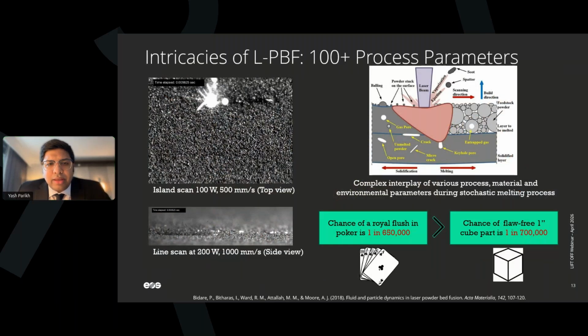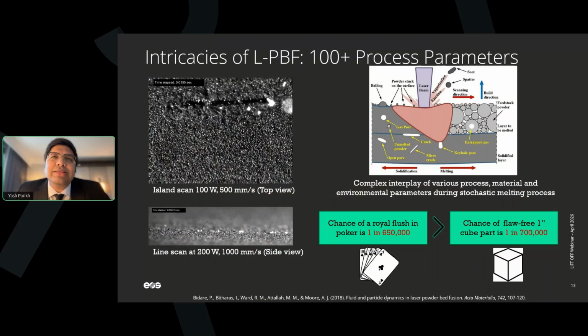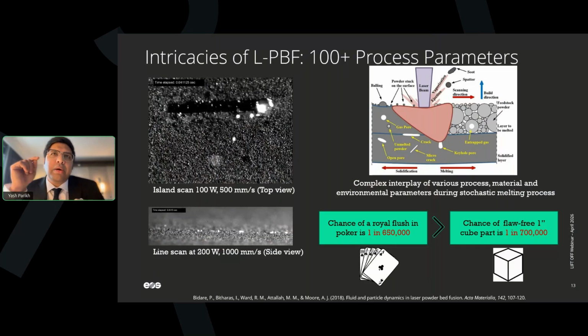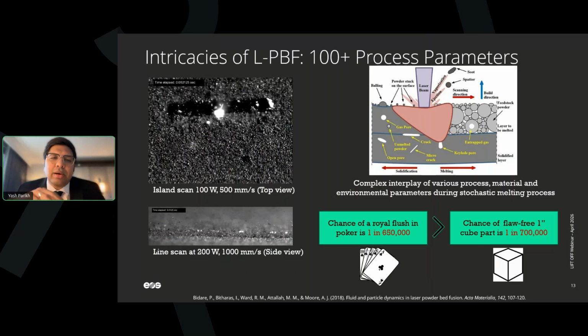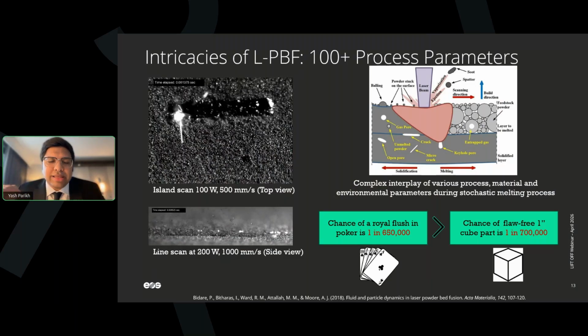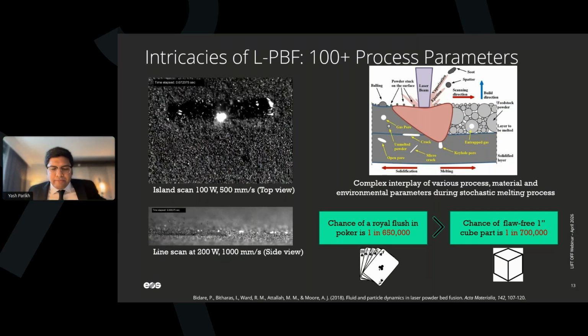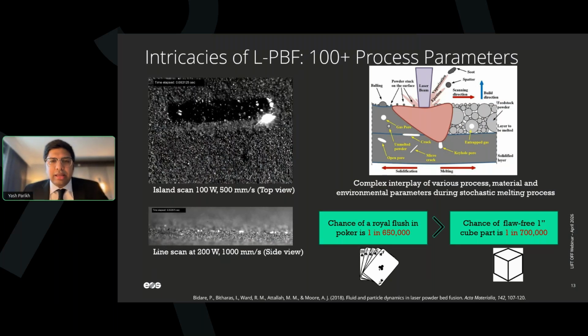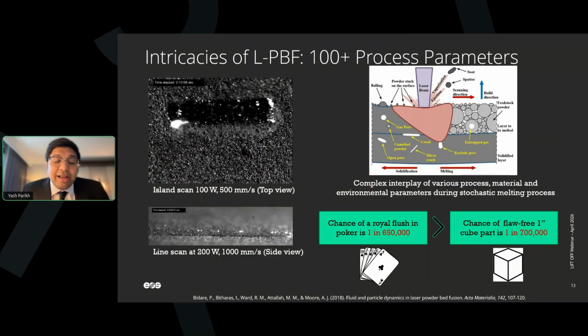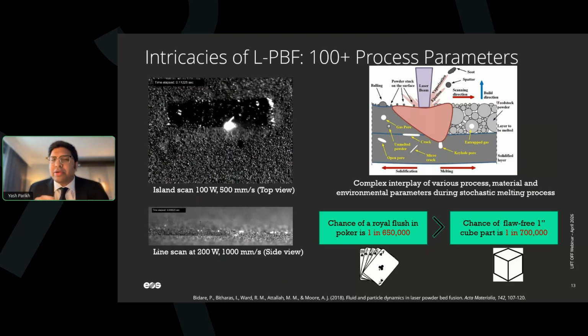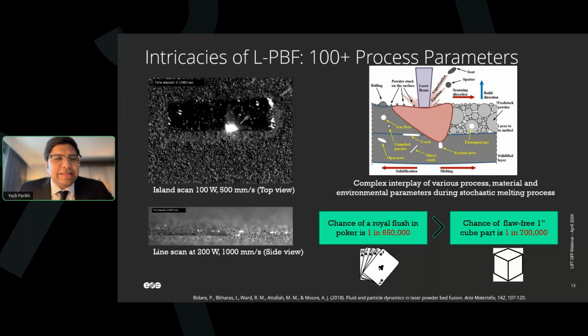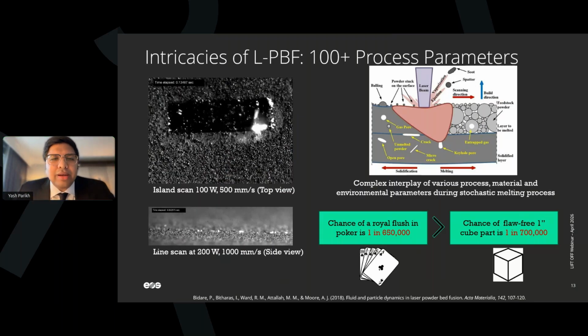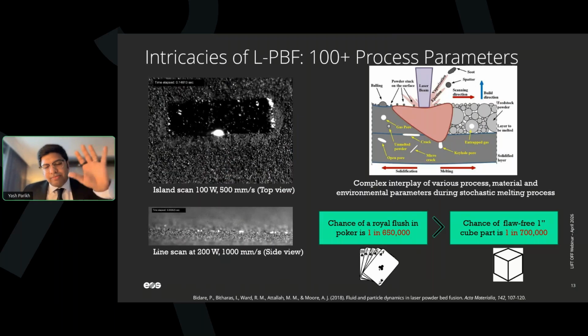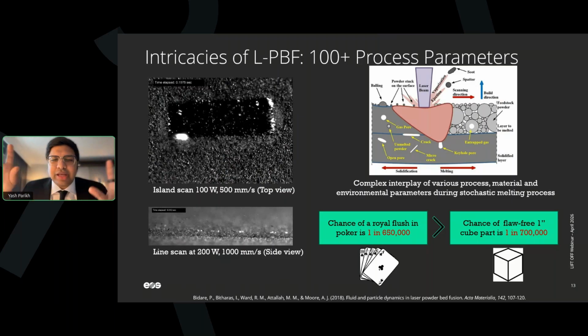And this is the reason. The laser powder bed fusion process itself is very complicated. On the left-hand side, you have a top view and a side view of the process. It's like a laser shooting on a powder bed and making it so volatile. Then on your right-hand side, you see a lot of things happening simultaneously. There are process parameters, and things happening around the spatter, the balling phenomena, the formation of gas pores, and so many other things that influence the outcome. You see the rastering pattern of the laser on the powder bed. Powder size distribution changes if you reuse it so many times, and you have a different behavior altogether. If you're using multiple lasers, then one laser's soot is in the way of the others, and so many other things are going on.